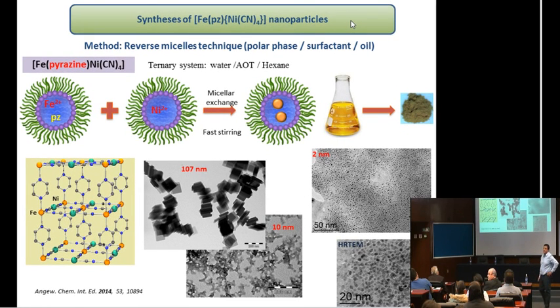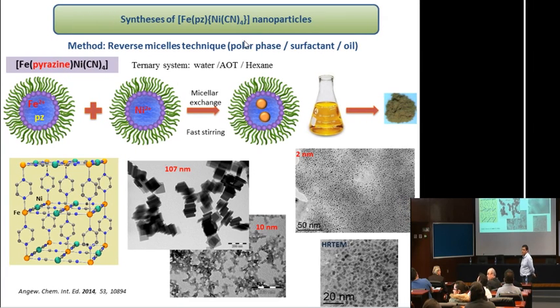So, if you make crystallization in a spin crossover state and make crystallization again in the second spin crossover state, will you have the same structure at the end? It depends on the complexes. It's possible to have a structural phase transition, which means in the low spin state and in the high spin state we'll have different structural phases. But sometimes you have the same structural phase, with just an increase of the volume. You have the two possibilities. It's really dependent on the material.